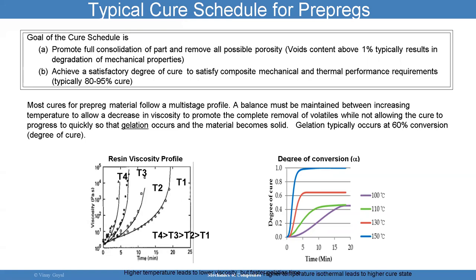Balance must be maintained between increasing temperature to allow a decrease in viscosity. So if you increase temperature, that will decrease the viscosity, and that will help you remove any volatiles, while not allowing full cure to progress too quickly so that gelation occurs and the material becomes solid. So it's a balance. And these ovens that I'm talking about are basically trying to achieve that balance. They're trying to remove the volatiles. They're trying to not get the cure too quickly. They're trying to make sure that there's cross-linking occurring. And all that needs to happen before the material becomes extremely solid.